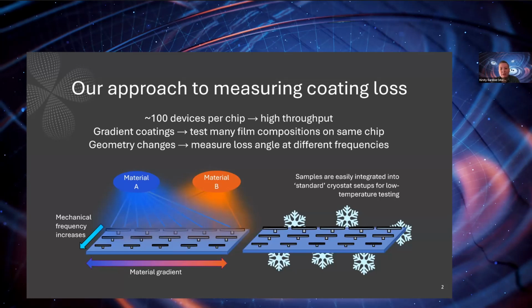Instead of using macroscopic mechanical resonators, our approach is to shrink everything down to microscale mechanical resonators. With, say, 100 devices per chip, you can very easily imagine doing high throughput testing of these devices and therefore of the thin film coatings on top of them. If we have gradient coatings, then we can test many different film compositions on the same chip. And it's really easy during fabrication to change the geometry of these microresonators so that we can measure the loss of the materials at different frequencies, again, all on the same chip.